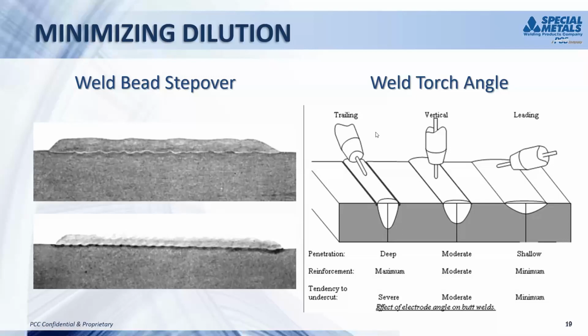One of the other tricks you can commonly do with some cladding processes is playing with your torch angle. A completely vertical torch will be a good blend between good penetration and good reinforcement. Now, if we angle our torch down to have a good leading torch angle, we're not burning into as much of the base metal. We're spreading the bead out a little bit, and we're going to minimize the problems with dilution. Both of those tricks, as well as welding uphill or downhill, can be very useful to minimize that dilution, so you're maximizing the corrosion resistance of the alloy you're putting down. Next slide.